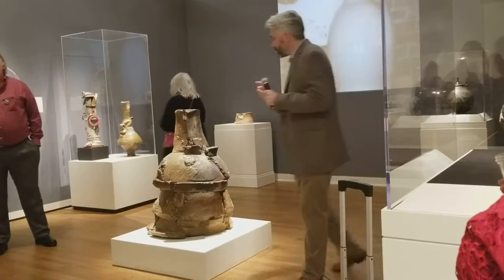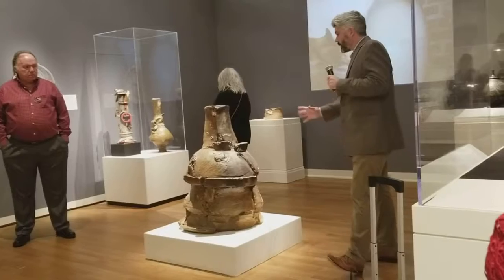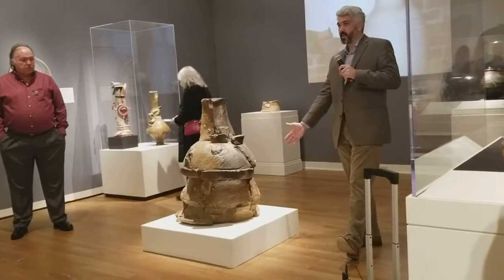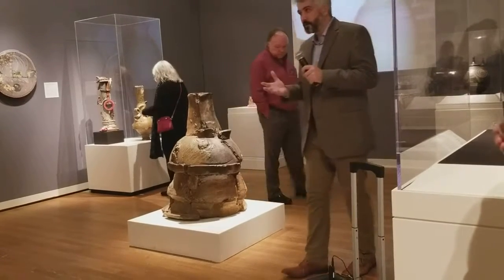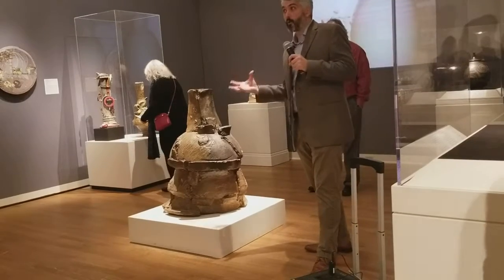When you evaluate something like this, you want to begin to look at all the little cues that the kiln is giving us — one of which are waddings. You see these three little wad marks? There are wads on the backside, because people use wads to support their pots in the kiln so that it doesn't stick to other pots. This whole piece was unglazed going into the kiln. Everything you see here is done from the ash that's being carried through the kiln. As the ash attacks the surface of the pot, it begins to melt and create its own glaze.